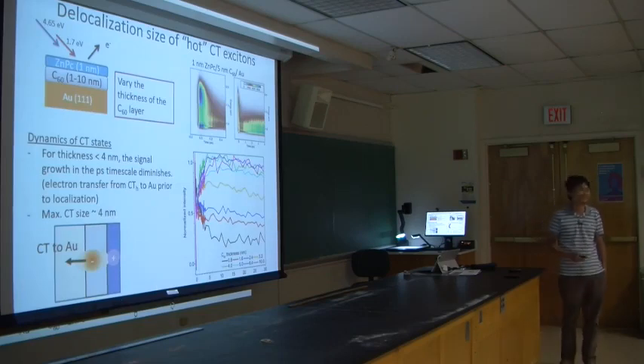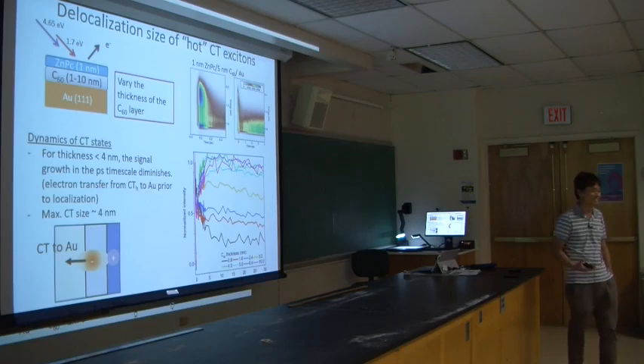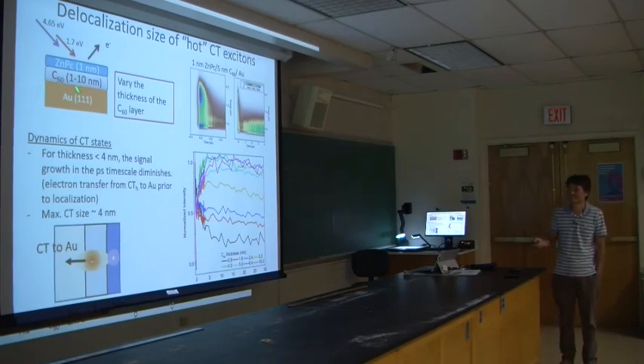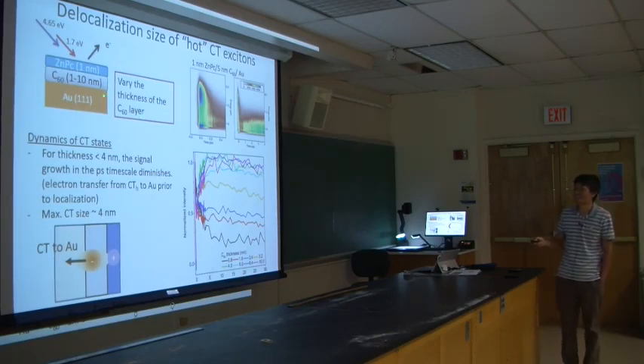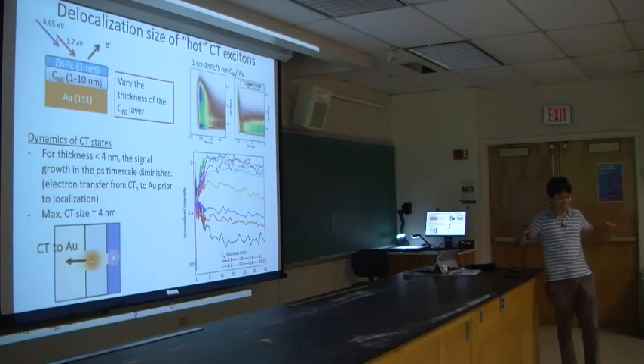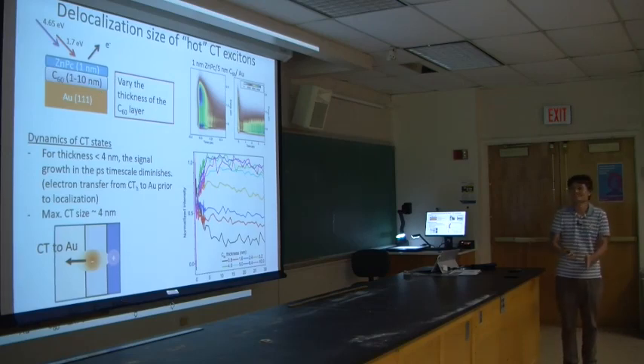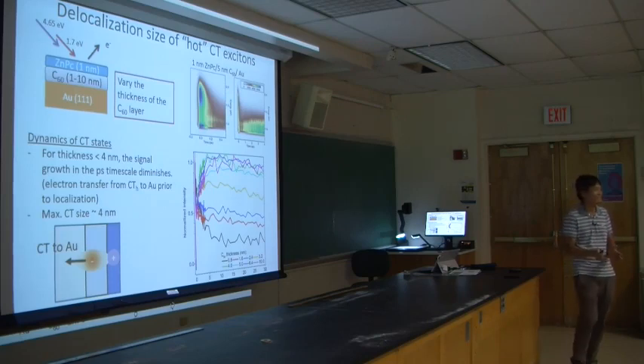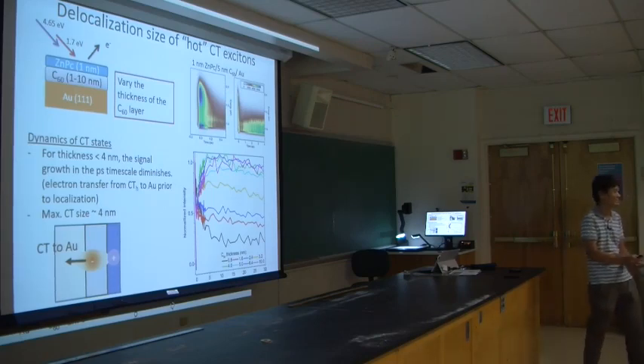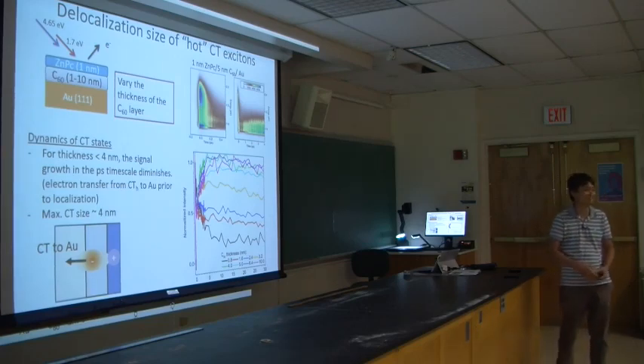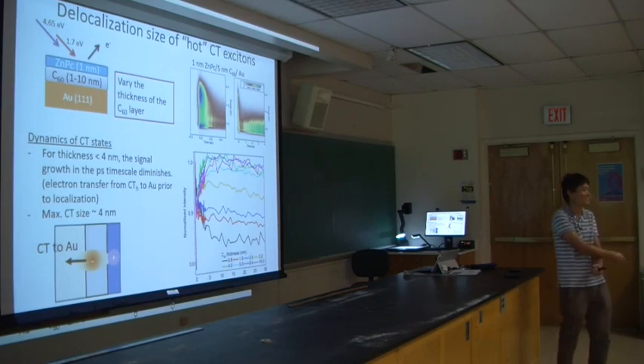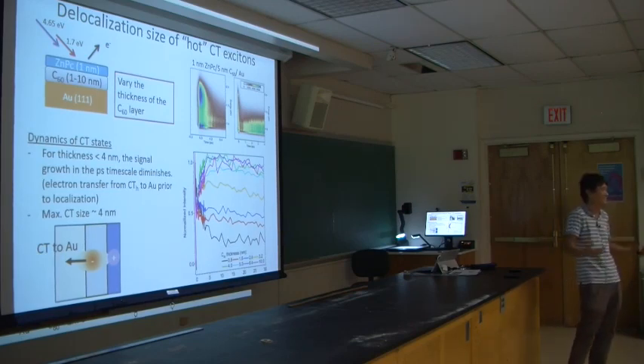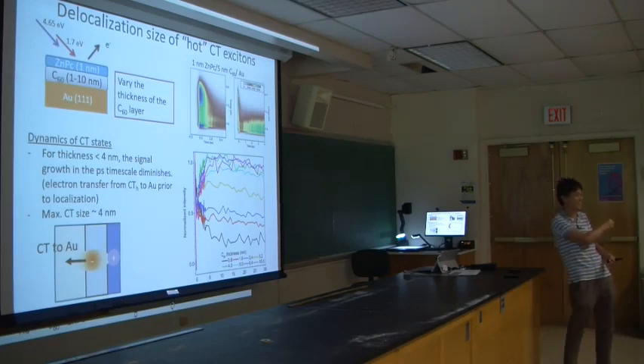We're also interested in measuring the size of this so-called hot CT state, right? So what we did is we changed the C60 layer thickness. For thicker films, we always see these rises in the picosecond time scale, right? The localization from this delocalized state to that localized state. Now as we make the C60 layer thinner and thinner, eventually this delocalized wave function will be in contact with the gold substrate, right? And if you are in contact with the gold substrate, the gold pulls the electron out from the CT state, right? Because gold is a metal, right? It has a bunch of empty states that can accept the electrons.